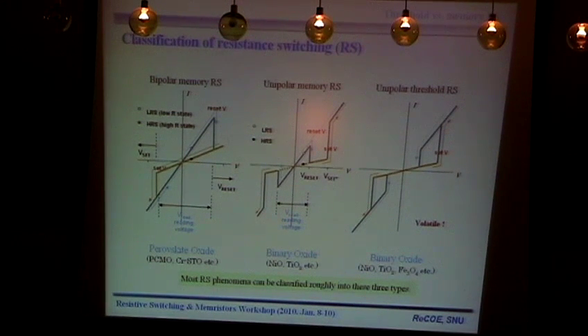On the other hand, in unipolar resistance switching, both the reset and set processes occur at one polarity. So it's basically symmetric about the polarities. But there's a little difference between memory switching and threshold switching. There are two states, the low resistance and the high resistance state.